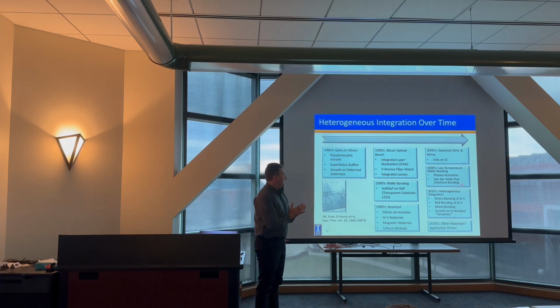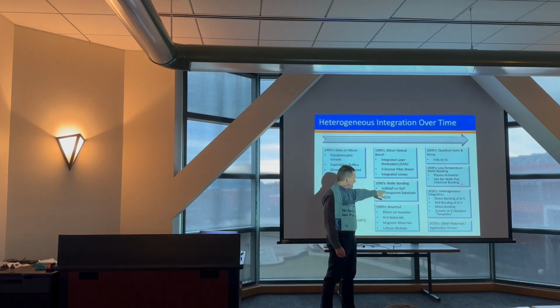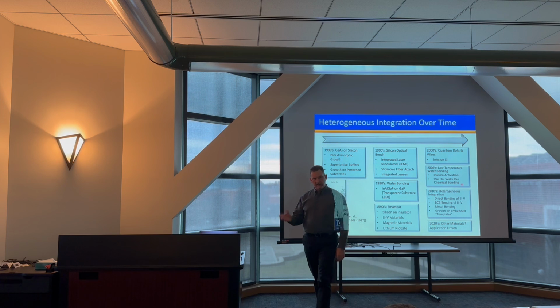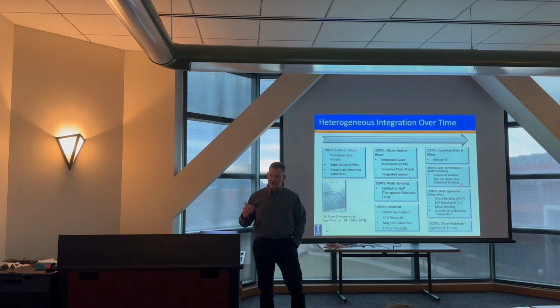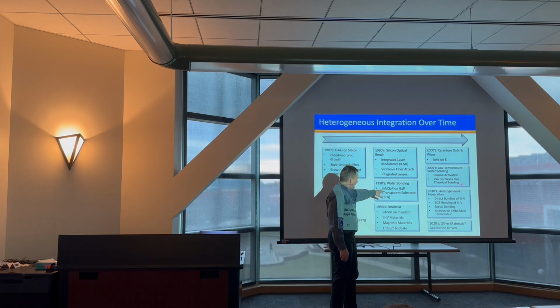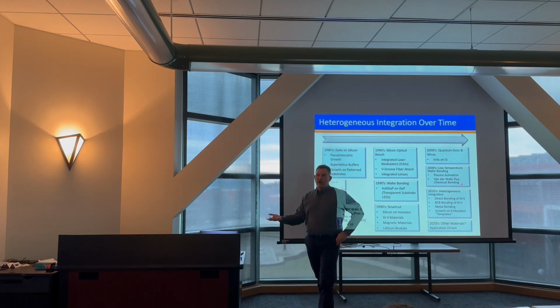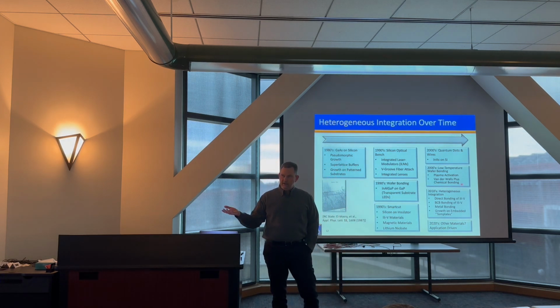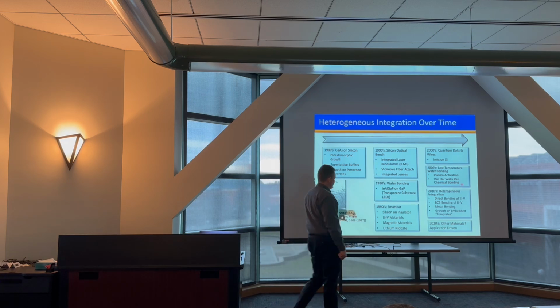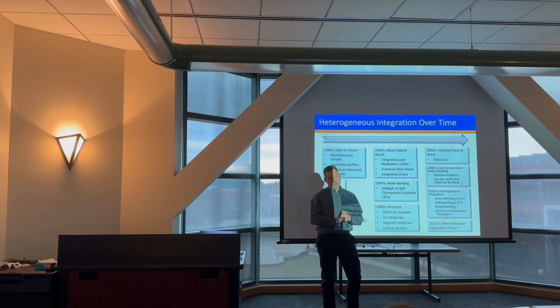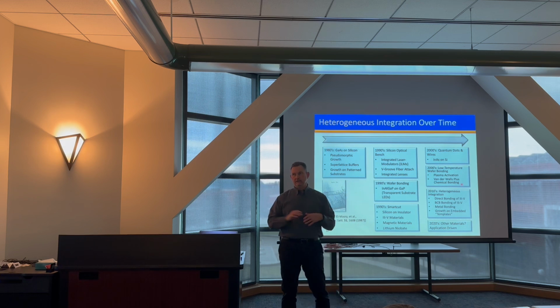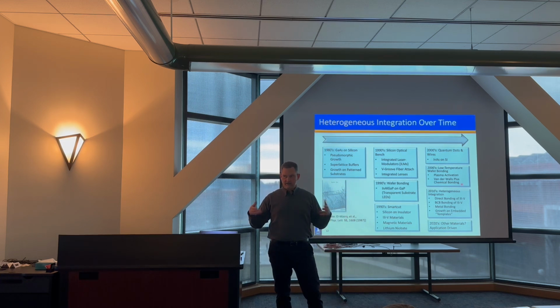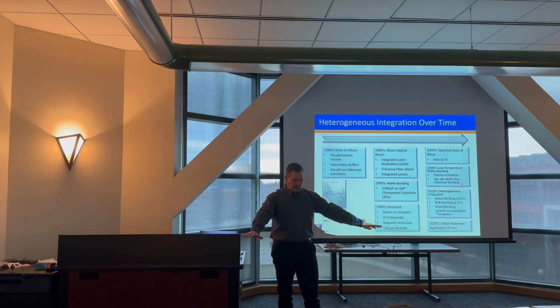Okay. So at that time, Hewlett Packard began bonding indium aluminum gallium phosphide LEDs onto transparent substrates. So they'd grow on gallium arsenide, right? Because indium aluminum gallium phosphide is lattice matched to gallium arsenide. But the problem with gallium arsenide is its band gap, right? It's going to absorb the photons that are generated by my red LEDs. So if I leave it on gallium arsenide, I lose half my photons, because again, they're going off into 4 pi steradians. I've got an island of opaque material below. I lose those photons, okay?